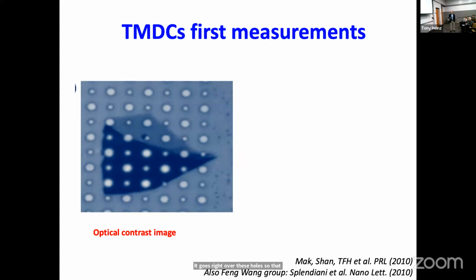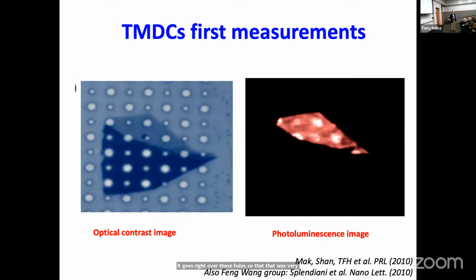But the part that was a bit surprising was when you looked at the emission spectra, instead of reflection, you illuminate with the laser and you look at the light that comes out. You saw a very strange effect, which is that you got quite a bit of light emission, bright emission from this thinnest part of the material, and you got basically no light emission from the thicker part.